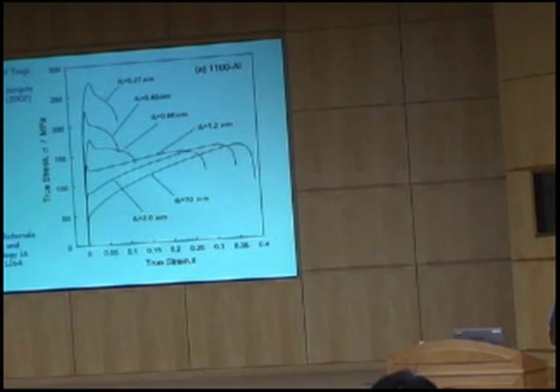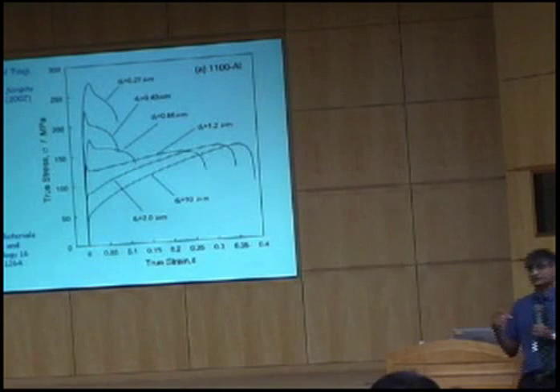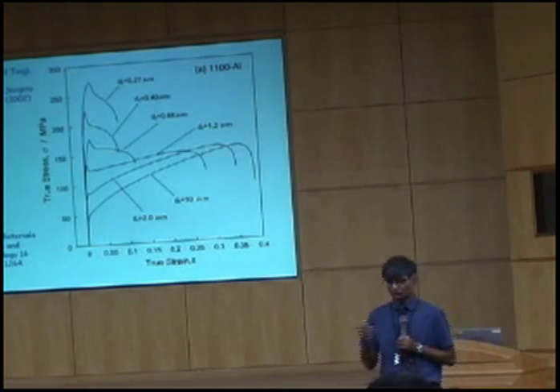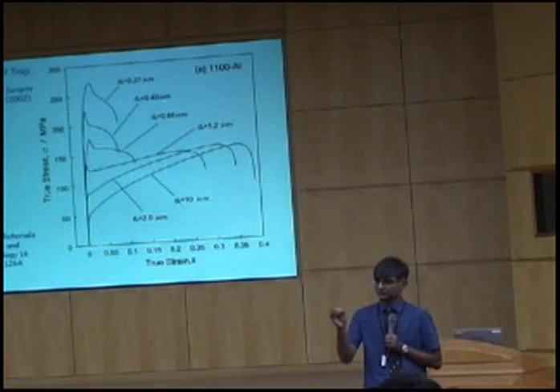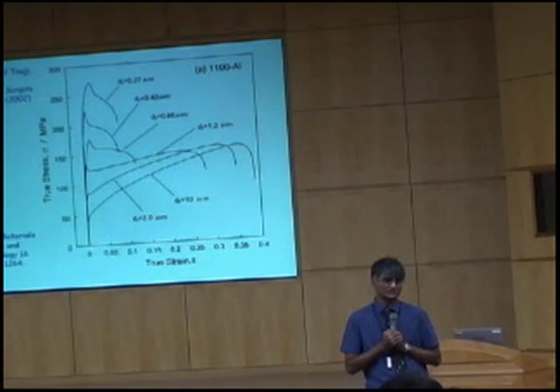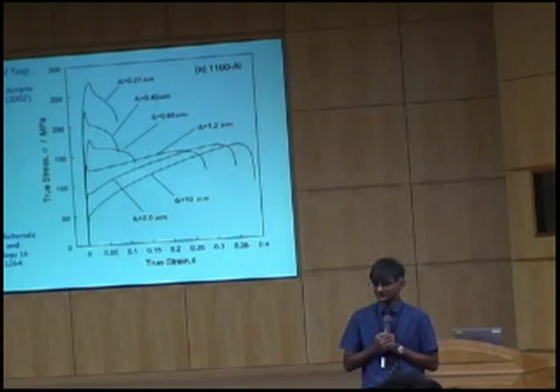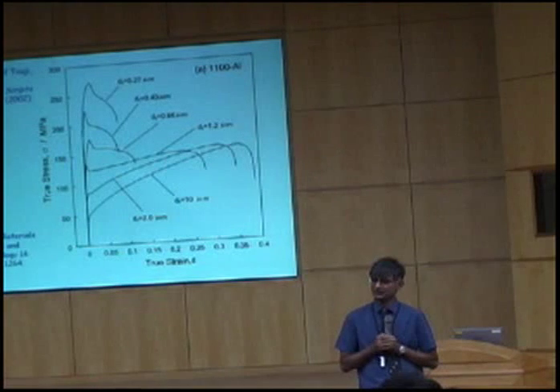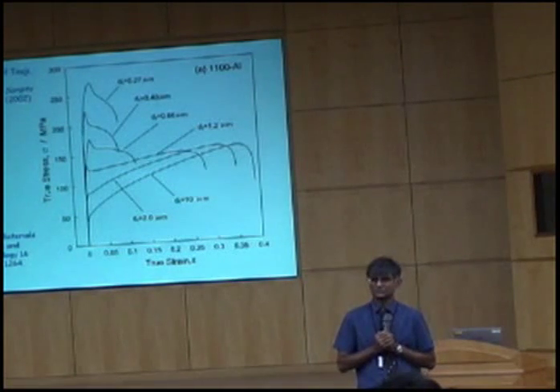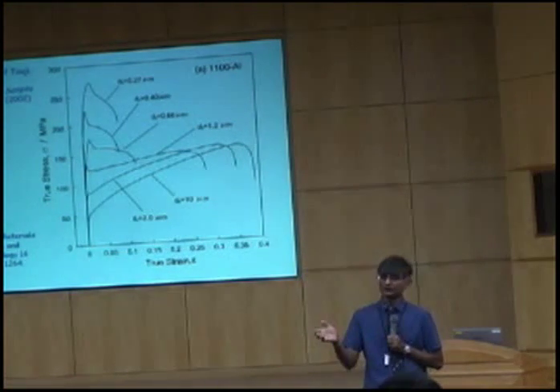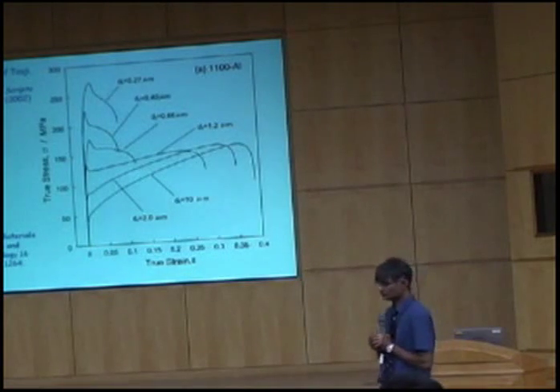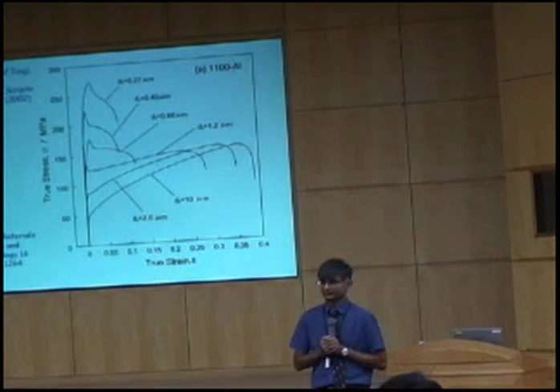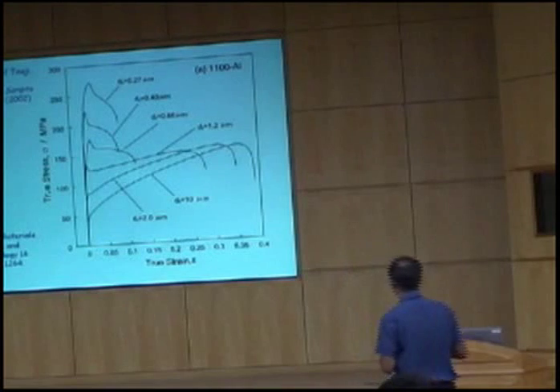Okay, fine grain size. There's been a lot of research all over the world to try and produce extremely fine grain structures in steel, in many other metallic alloys. And all of that research, I would say, if you talk about going to grain sizes less than 1 micrometer, has failed. Okay? And it has failed because of this reason.